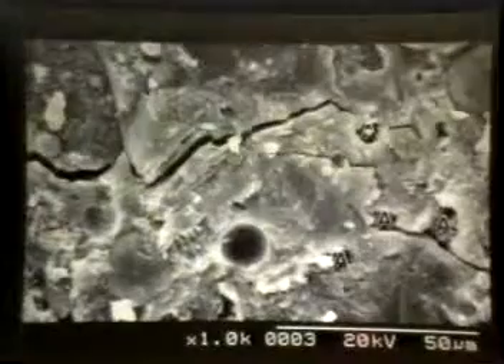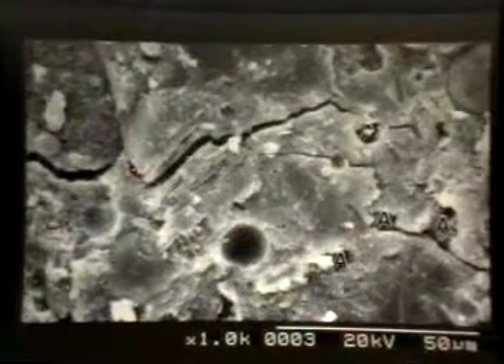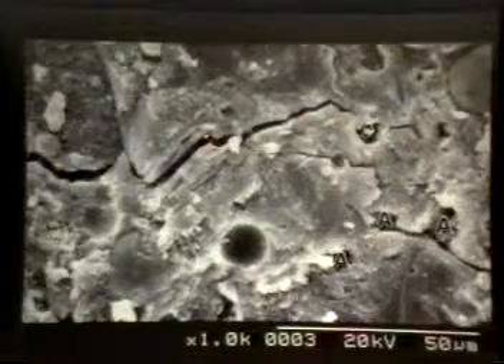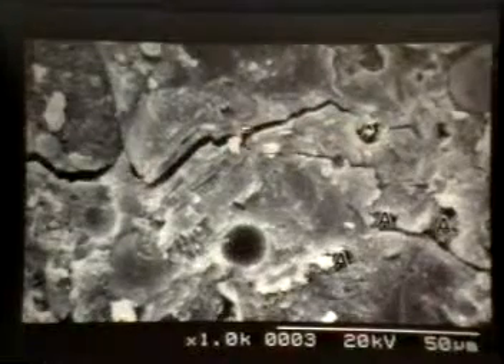Whereas this is what you call an autogenous shrinkage crack, which occurs during the hydration of cement. You cannot avoid it. You have some hydration going, lime crystals forming. At the same time, you have the cracks forming. And then you have the thermal cracks. As you go deeper inside a mass concrete structure, you will see that the amplitude of these cracks will increase, the width will increase, the frequency will increase. And then, of course, this is what we mean by autogenous shrinkage cracks. As you can see under the scanning electron microscope, this is what it would look like.